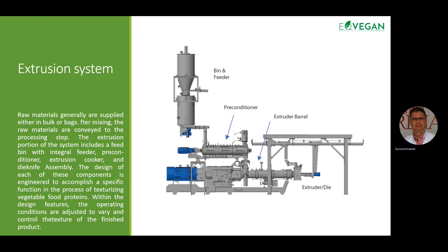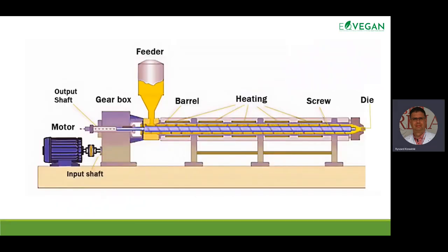Preconditioner. Without preconditioning, it can be challenging to produce texturized vegetable proteins with good laminar structure. Vegetable proteins that are not preconditioned have a strong tendency to expand rather than laminate due to non-uniform moisture penetration that does not allow alignment of protein molecules. Uniform and complete moisture penetration of raw ingredients significantly improves the stability of the extruder and final product quality. In addition, by completely plasticizing the raw material particles prior to their introduction into the extruder, wear caused by abrasive material particles is greatly reduced.